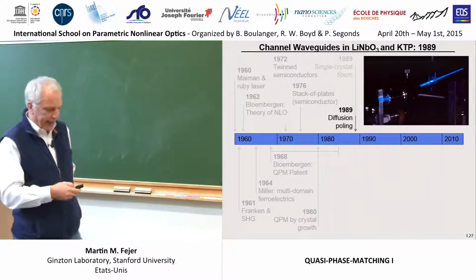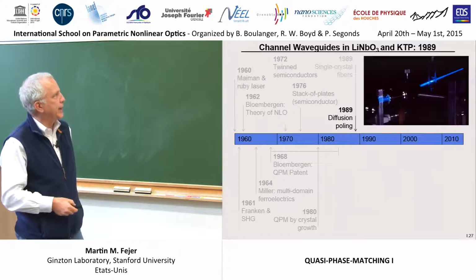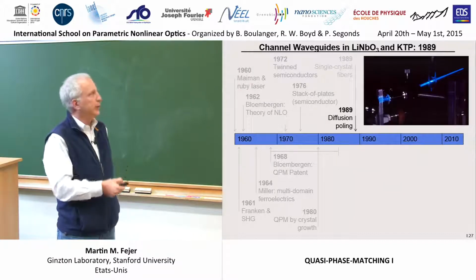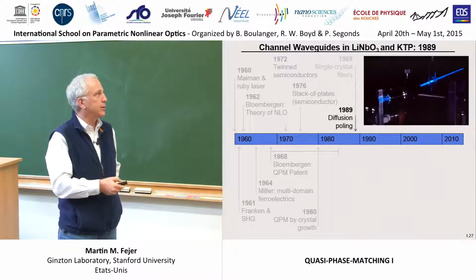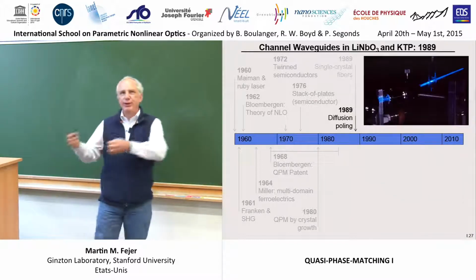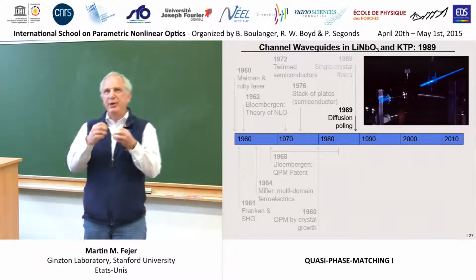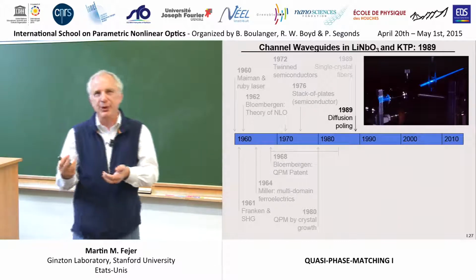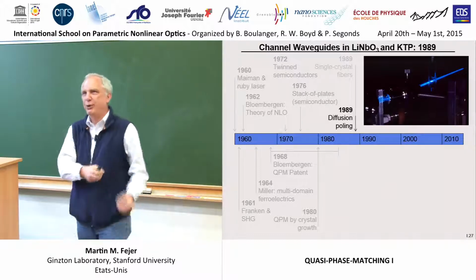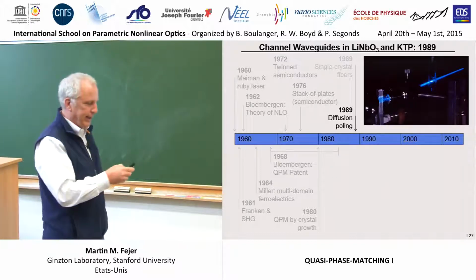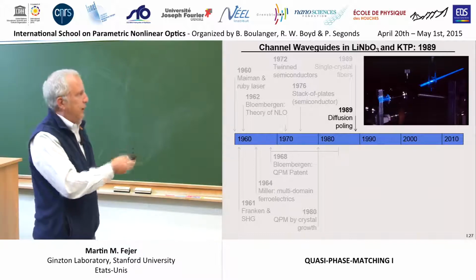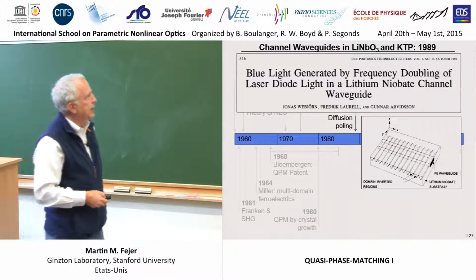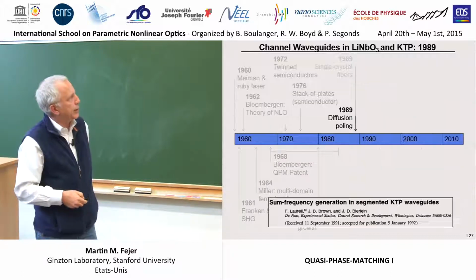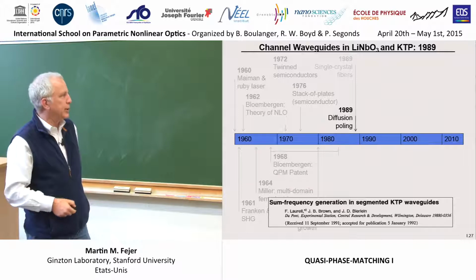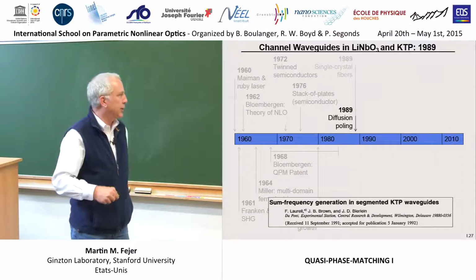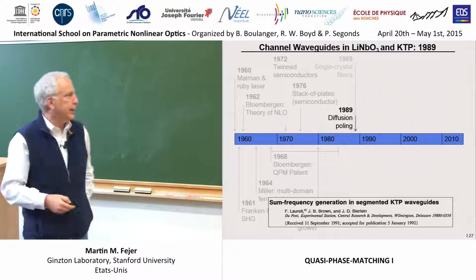Quickly, channel waveguides emerged. Blue light generation. A lot of the driving force was that this was prior to the advent of gallium nitride lasers, and there was a lot of work figuring out how you could make a compact source of blue light for things like optical data storage by doubling infrared semiconductor lasers, and so you needed an efficient compact device. And so getting to 400 nanometers here was of interest, and again, similar work nearly at the same time in the Royal Institute. And KTP was periodically poled, though they didn't know it at the time, by Laurell and Bierlein at DuPont.